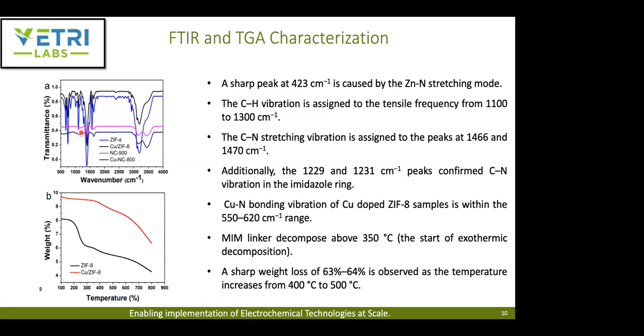Also, a couple of other CH vibrations were assigned from the peak at 1100 to 1300, and the stretching vibration is for the peak at 1466 and 1470. And additionally, there were two other peaks at 1229 and 1231, confirming the C-N bond in this imidazole ring. And also the copper-nitrogen bonding was confirmed within this range of about 550 to 620 centimeter inverse.